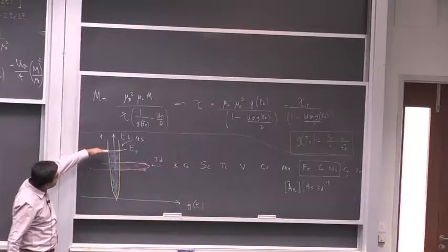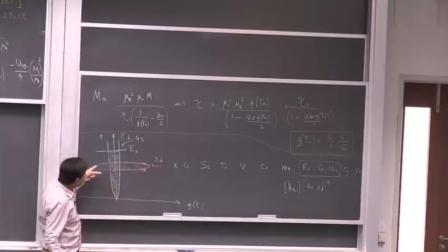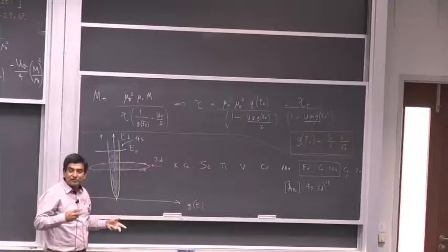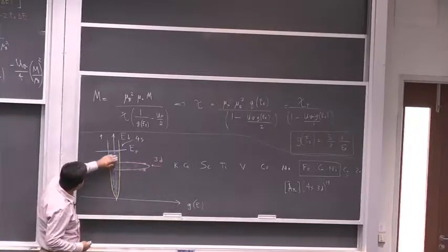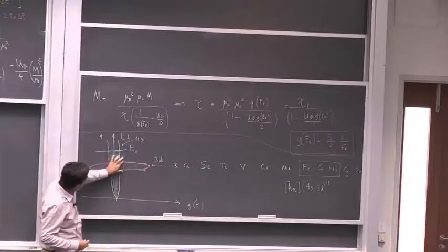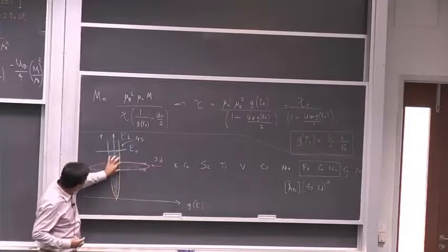So all the 11 electrons in the 4s 3d bands share energy. The electrons can be shared between the 4s and the 3d band, because in this region of energy the wave functions overlap. So the 4s and the 3d bands are going to hybridize in this region.